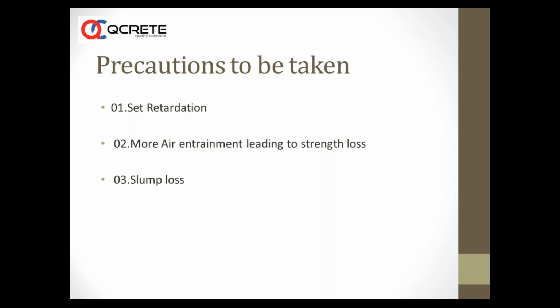One thing we are very sure of, earlier days, for example, consider some cases which happened in 1993 to say 1996 or 98, where lignosulfonate based plasticizer cum retarder were used. In Delhi, we had seen a girder was cast and the concrete did not set for almost 1 week. The concrete could be taken, scooped out, and we could recast the cubes after 3 days. More cubes were cast, but we could not dispose of them. The company could not take away the girder, and even the contractor was not interested in taking away the girder which was cast, because it was a crowded area.